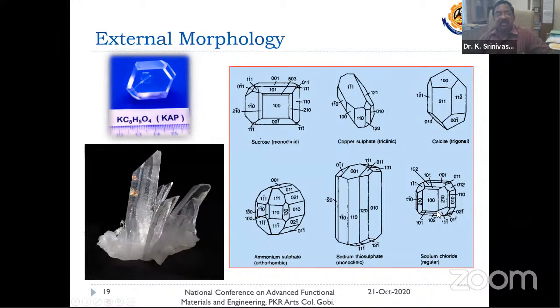These morphologies are very, very important for several of the smaller size crystalline materials. For example, for some medical applications, pharmaceutical applications, we may need spherical type of particles. We may need needle type of particles. So there, you need to adjust the growth along a particular orientation. You need to arrest the growth along a particular direction. So you can change the morphology by modifying the growth conditions, by adding specific additives, etc. By controlling the growth velocities along different directions, you can change the morphology as per your requirement.